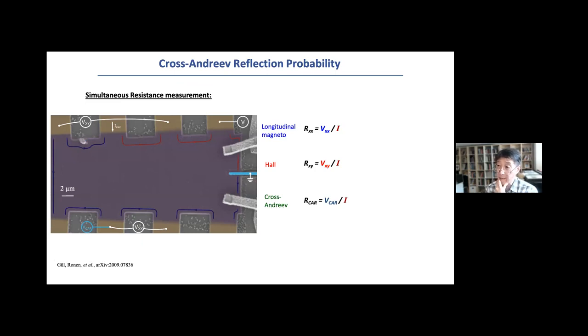Right, so the measurement scheme is the following. As I said, we will inject the current from the upstream. So there's current to bring it down, and the superconductor is always grounded, such that the current is always drained through the superconductor. In the downstream, basically we can monitor the chemical potentials to see the downstream chemical potentials. At the same time, we can measure the Rxx and Rxy using this voltage probe and carefully delineate this contact, the equilibration problems throughout this.